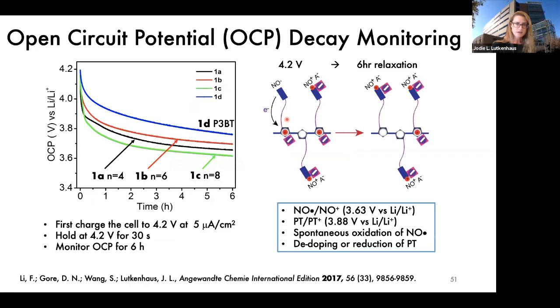The reason is that the TEMPO radical has one given redox potential of 3.6. The polythiophene backbone in our hands has some redox potential of 3.8. And so because they have mismatched potentials, when you start to reduce and oxidize the electrode as a whole, you have internal electron transfer between the 2 species.